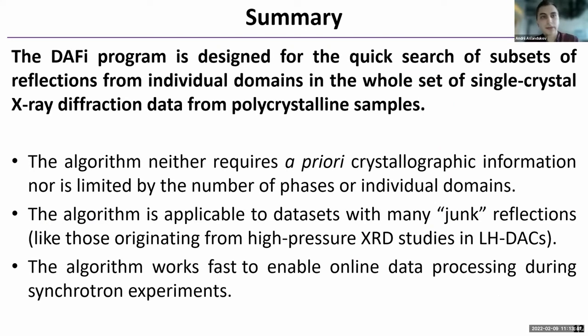So, in summary, the DAFi program is designed for the quick search of subsets of reflections from individual single crystal domains in the whole set of single crystal X-ray diffraction data from polycrystalline samples. The algorithm finds these groups purely geometrically. That's why it neither requires a priori crystallographic information nor is limited by the number of phases or individual domains. The algorithm is applicable to datasets with many junk reflections, like in the example of the laser heated diamond anvil cell. And it works very fast to enable online data processing during synchrotron experiments.